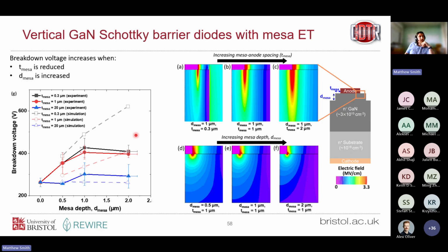So actually, when we do simulate these devices, we find that compared to our experimental data, so experimental data is these solid lines here, and now we've got MESA depth on the x-axis. It should be the case that as we keep going deeper, since we make our MESA deeper and deeper, we should still see an increase. We should keep seeing an increase in our breakdown voltage. What we find experimentally is that it saturates somewhere between 1 and 2 microns of our MESA depth. And we don't see that in simulation.